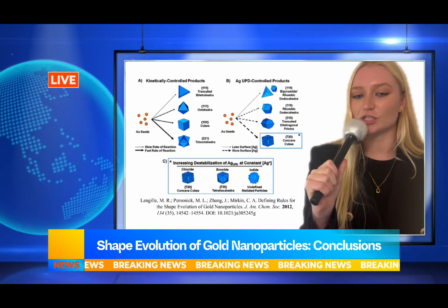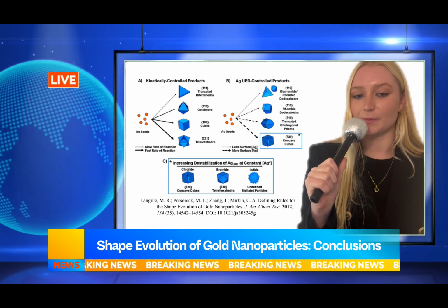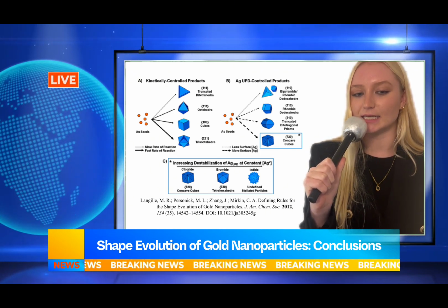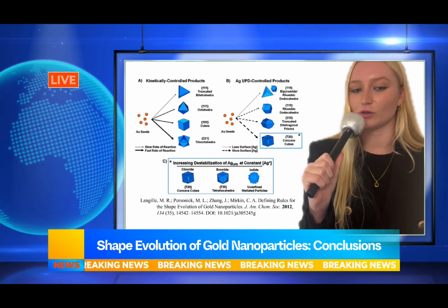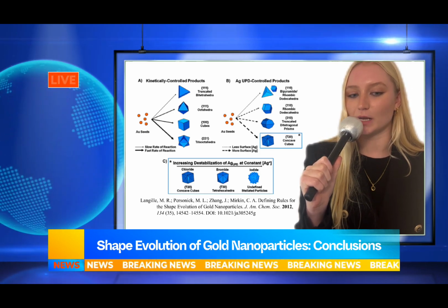destabilized. Fifth, high concentrations of larger halides hinder silver deposition, limiting accessible morphologies. Lastly, kinetic trapping due to the underpotential deposition layer in chloride surfactant enables access to a broader range of morphologies.